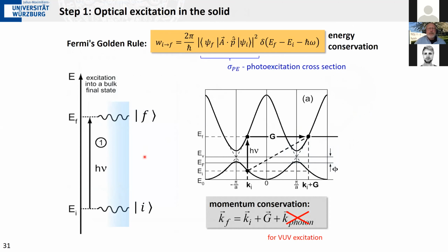This is shown here. That's an easy one because we do not know anything about the surface yet. We describe the transition from the initial state to the final state, and we do this by Fermi's golden rule. This is just time-dependent perturbation theory. We have the Hamiltonian that describes our crystal, our electrons in the crystal, which gives us the Bloch states as the eigenstates of our unperturbed Hamiltonian. And then we add our photon field as a small perturbation, time-dependent perturbation. It's an oscillatory electrical field with frequency omega. And then Fermi's golden rule tells us that we have a certain transition rate from the initial state to the final state, which is basically given by this matrix element squared,